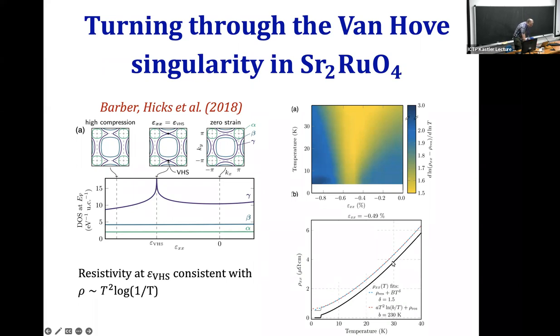Okay, and this is the actual resistivity as a function of temperature. Okay, the black one is just shifted. Okay, this one is the actual data, right at the Van Hove strain. So this is as a function of temperature at the Van Hove strain. And in this paper, they actually tried to fit it either to T to the power 1.5 or to T squared log T. And it turns out over this range of temperature, okay, from Tc, which is enhanced close to the Van Hove singularity, 3 Kelvin up to 40 Kelvin, it actually fits more or less equally well both forms. There's a more recent experiment actually by the same group, by Clifford Hicks and company, where they suppress superconductivity by a field, and they actually find that T squared log T actually fits the data visibly better than T to the power 1.5.